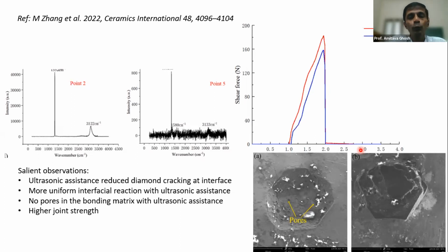But the bottlenecks, of course, that have been noted, since the interaction is there with a very high amount of peak power, the localized temperature goes up much more than whatever is required. That is how the researchers so far are reporting. But perhaps we need to control that, and that can be controlled much more efficiently if we replace a continuous wave laser by a nanosecond or femtosecond pulse laser, by controlling the peak power, the pulse width, the pulse frequency. Okay, and if we can really do that, we would be able to avoid the graphitization that is taking place, and of course the interface and all those things can be made much smoother, uniform, and much stronger. That is the takeaway points from the reported literature so far.